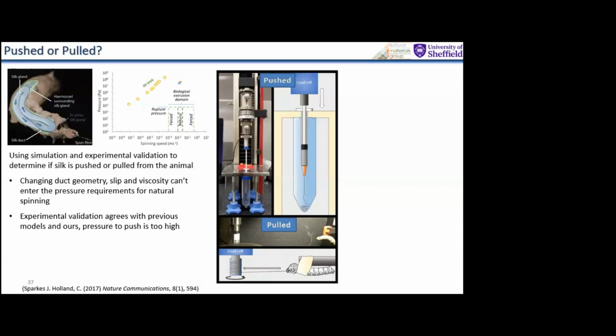We know the cross-sectional area of that fibre, and therefore we can measure the pressure, the forces required to pull silk out of a silkworm. And we found out it's perfectly possible to pull silk, and the forces required are achievable, but the forces to squeeze silk aren't. So it's not extrusion, it's pultrusion. And so if anyone says spiders squeeze out silk, you can say no, they would pop. And silk is mostly pulled from the animal.